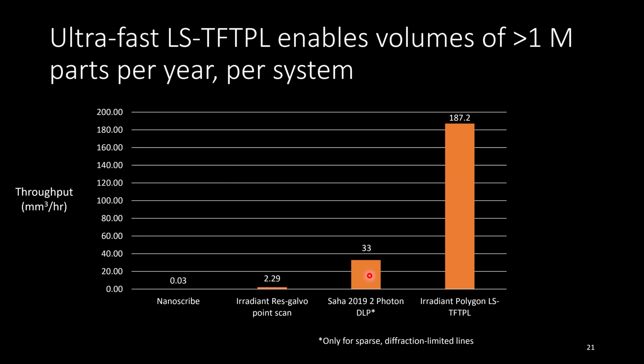And so if you compare the throughput, this really enables the scale that can make things practical. So I talked about Nanoscribe before. These sorts of point scan systems have a maximum throughput at their highest resolution of about 0.03 cubic millimeters per hour. We do use point scan prototyping systems. You can use faster scanning like resonant scanners. These can go about 100 times faster. So you can get 2 to 3 cubic millimeters per hour.